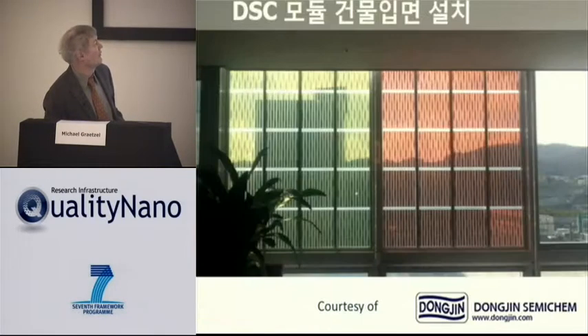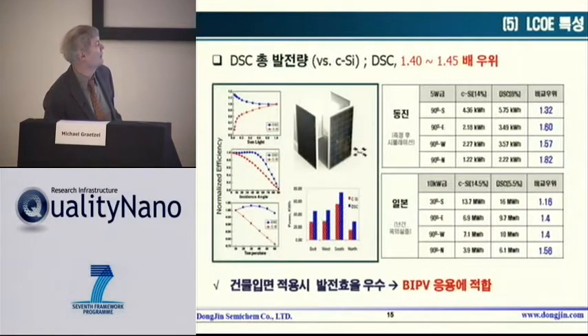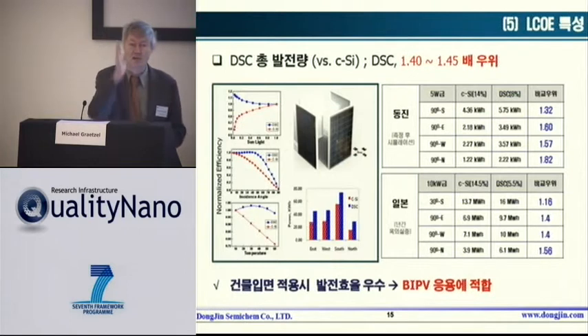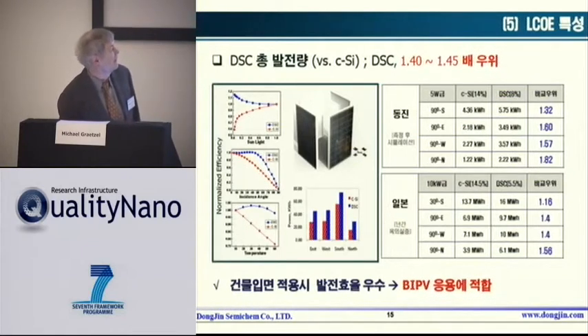So more of those booths, and I showed you the Korean panels already. So what has come out of these studies is that if you take a panel and mount it vertically, now you check. Suppose you have equally rated panels, a silicon panel that is rated 100 peak watt, and a dye-sensitized rated 100 peak watt. And now you compare the energy output when you mount those two panels vertically. You can see there's always an advantage. This is the relative advantage. Can be 82%.